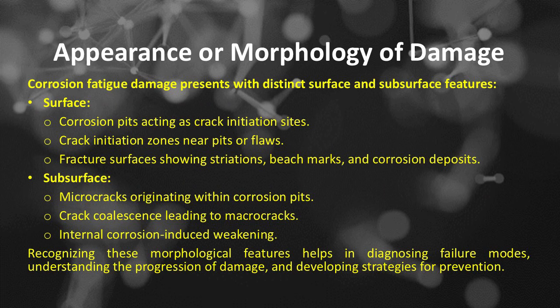Corrosion fatigue damage presents with distinct surface and subsurface features. On the surface: corrosion pits acting as crack initiation sites, crack initiation zones near pits or flaws, and fracture surfaces showing striations, beach marks, and corrosion deposits. In the subsurface: microcracks originating within corrosion pits, crack coalescence leading to macrocracks, and internal corrosion-induced weakening. Recognizing these morphological features helps in diagnosing failure modes, understanding the progression of damage, and developing strategies for prevention.